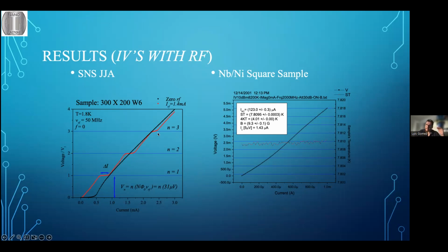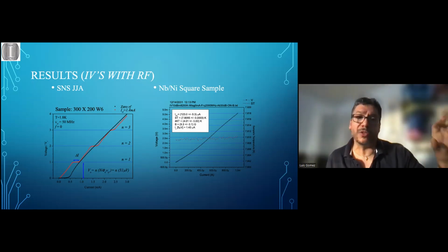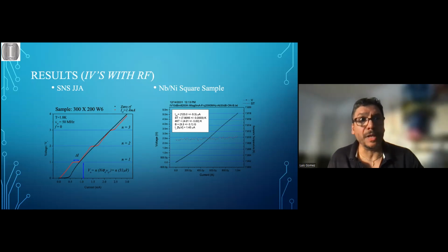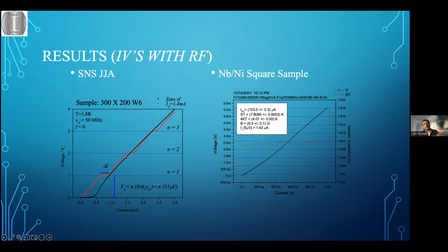There are very precise values of voltage where a plateau will appear that correspond to the frequency of the AC signal that is added to the system. In this case, I added, let's see, 50 megahertz of AC signal, and using the equations we can see that we have these plateaus at very precise values. And this is one of the beauties about the classical Josephson junction arrays made with niobium on top of gold film. This is the remarkable correspondence between the experimental values and the prediction of the theory.